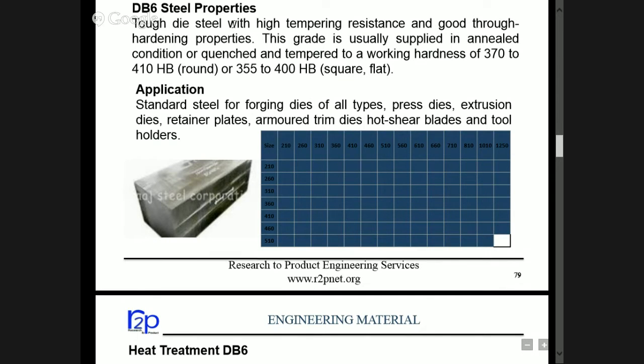DB6 steel properties: tough die steel with high tempering resistance and good through hardening properties. This grade is usually supplied in annealed condition or hardened and tempered to a hardness of 370 to 410 or less. Application: standard steel for forging dies of all types, press dies, extrusion dies, retainer plates, armor trim dies, hot shear blades, and tool holders.